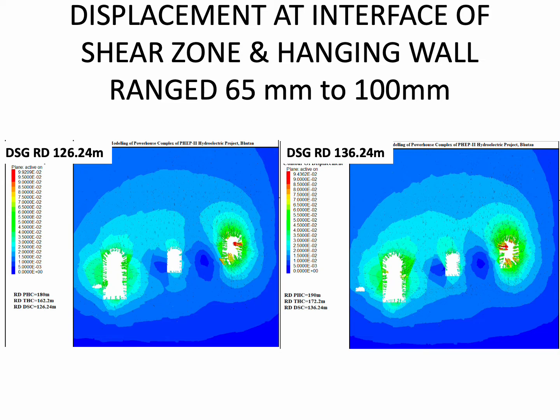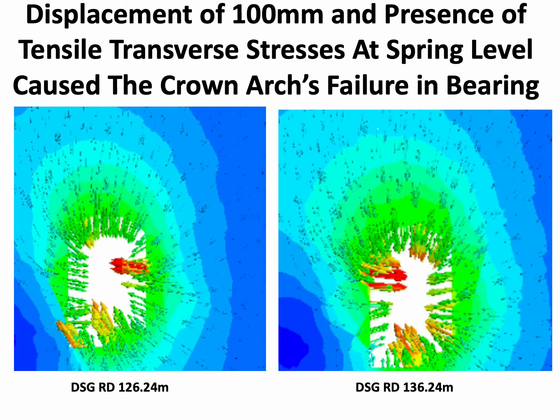Here in the downstream surge gallery, we see the displacements are of the order of 65 to 100 mm. We'll see it in the next slide. So in the downstream wall, if we see at the SPL level, these are the displacements of the order of 10 centimeter, and in the upstream wall and the crown, the displacements are again of the order of 10 centimeter at RD 126 to 136 meter. That means immediately after the shear zone, the rock mass lying at the SPL had undergone displacements of the order of 10 centimeters.